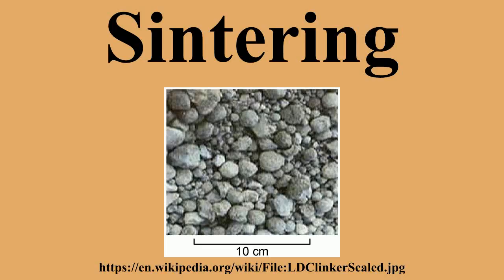Spark plasma sintering. In spark plasma sintering, external pressure and an electric field are applied simultaneously to enhance the densification of the metallic or ceramic powder compacts. This densification uses lower temperatures and a shorter amount of time than typical sintering. For a number of years, it was speculated that the existence of sparks or plasma between particles could aid sintering. However, Hulbert and co-workers systematically proved that the electric parameters used during spark plasma sintering make it unlikely. In light of this, the name spark plasma sintering has been rendered obsolete. Terms such as field-assisted sintering technique, electric field-assisted sintering, and direct current sintering have been implemented by the sintering community. Using a DC pulse as the electric current, spark plasma, spark impact pressure, Joule heating, and an electrical field diffusion effect would be created.